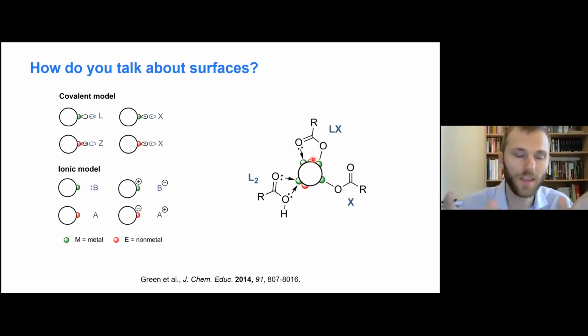So when I think about ligand exchange, there are lots of parameters that play a role. One of them is binding affinity, but the other one is solubility. If you have two ligands, and you're trying to look at the competition with the surface, and they have the same binding group, for example, but one of them has a lower solubility than the other one, then the one with the lowest solubility will bind to the surface because its chemical potential will be lowest there, and the one that is most soluble will have the lowest chemical potential in solution. So solubility really plays a role.